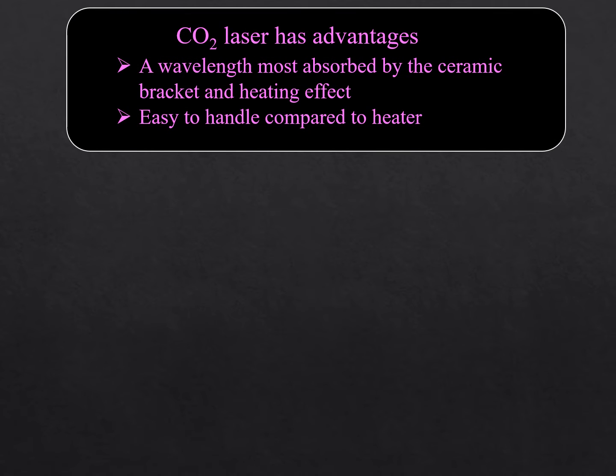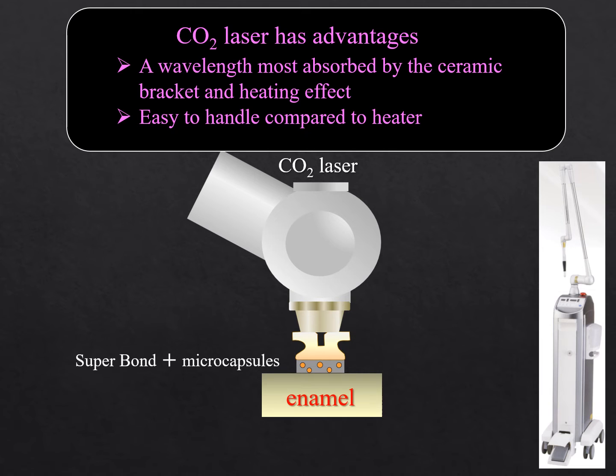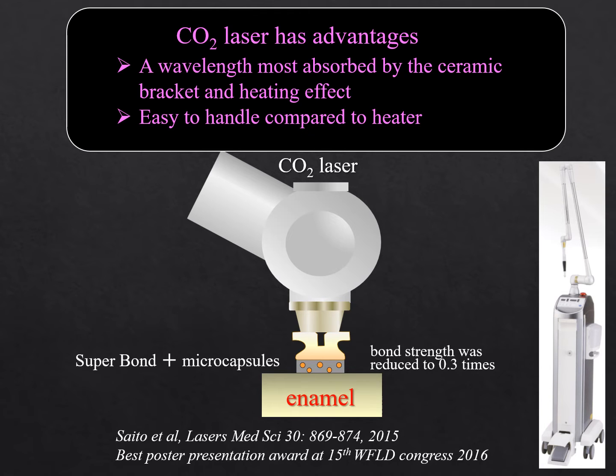In recent years, dental lasers have become widespread and many clinics have various laser devices. Among them, the CO2 laser has an advantage. Especially, it has a wavelength most easily absorbed by the ceramic bracket and has a heating effect. When a similar experiment was conducted using CO2 laser irradiation instead of a heater on a ceramic bracket bonded with Super-Bond containing microcapsules, the bond strength was significantly reduced to 0.3 times. It means the laser irradiation was effective to expand the microcapsules by heating.